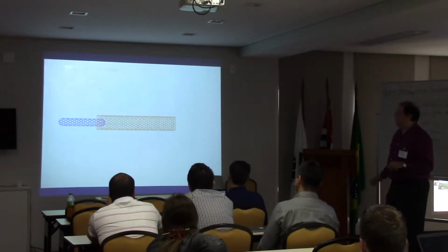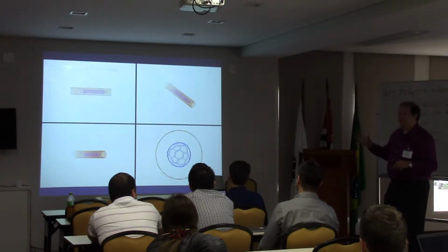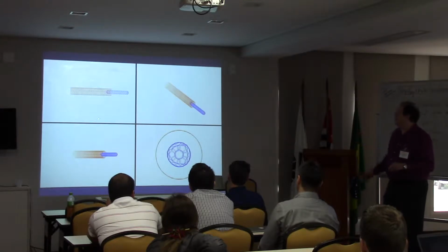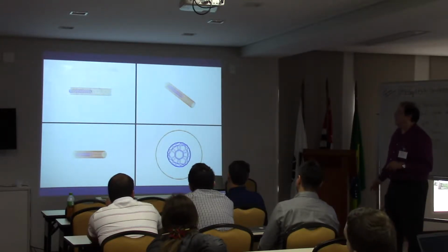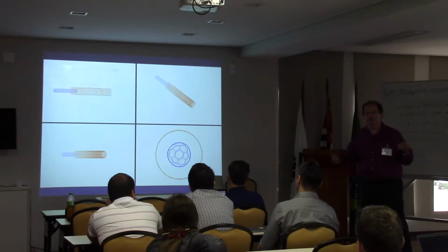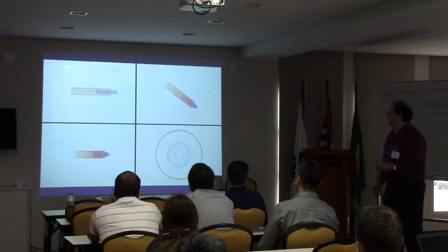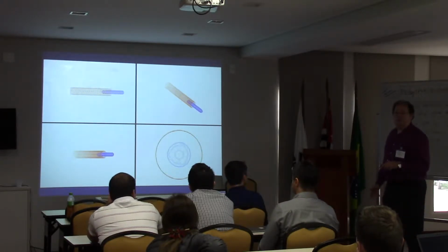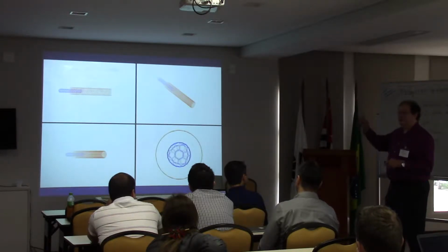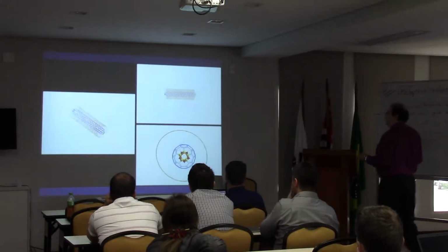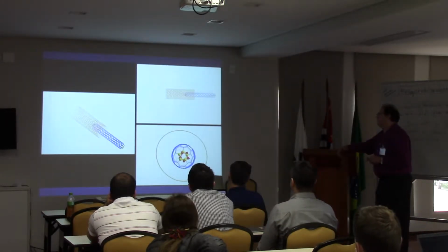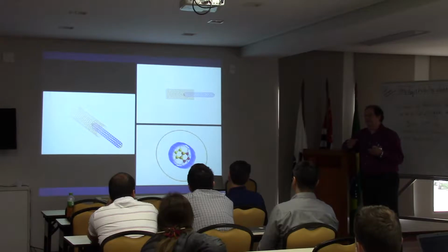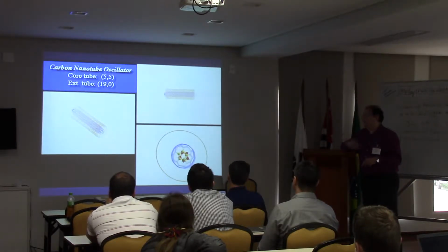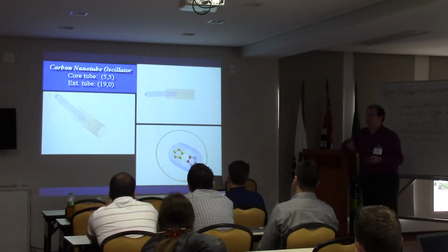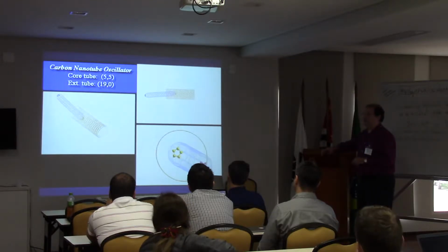One interesting point: this is not a standard oscillator, because the frequency is dependent not only on the geometry as in a standard oscillator, but also, when the tube is inside the other, there is no force. So the frequency can be tuned by exploiting the geometry. When you do the same simulation where the coupling is not perfect, you start to have exchange of energy and momentum between the tubes, and the oscillation is compromised.